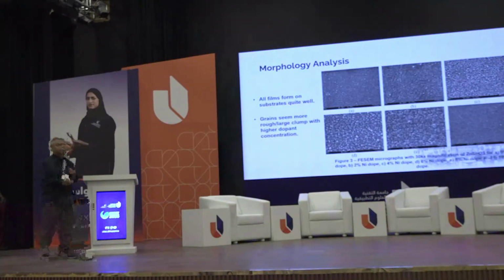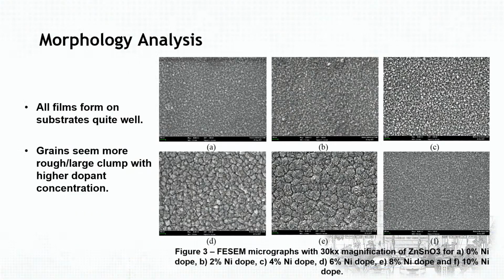is with some results in morphology analysis where the film is homogeneous on the layer. Then we can see the grain size, roughness of the material with the doping on the glass substrate. So we do some different ratios of doping from 0 to 10. Okay.